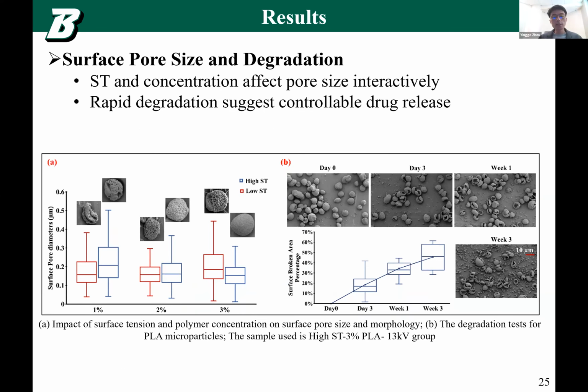And then we also investigate those factors' influence on the surface pores, because we want to know how big the surface pores are and how we can control the surface pores. Looks like surface tension and concentration affect the surface pores interactively.